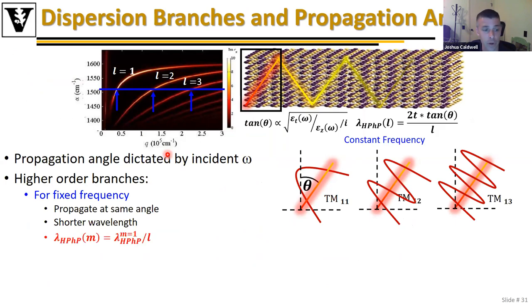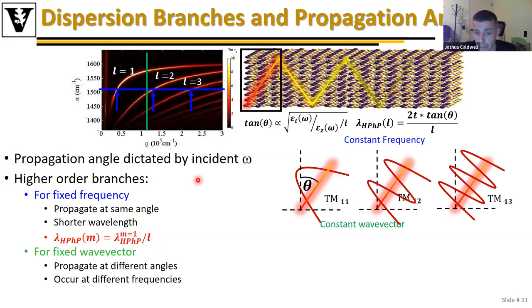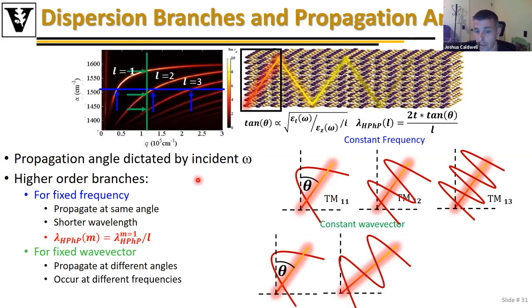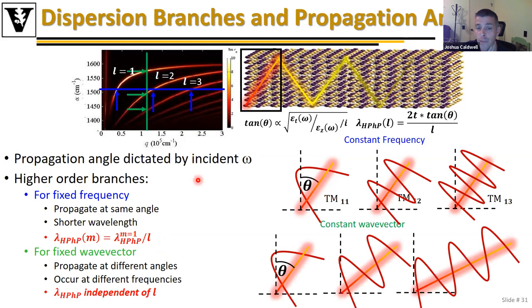And you can figure out the wavelength of that mode by looking at which mode you're talking about and the overall modal number that you're looking at. If I look at a constant wave vector, I now need to tilt that angle of propagation to support that same wavelength, but multiple orders of that mode, hence leading to this overall discrete structure as shown here. One of the interesting aspects of this is that your dispersion is therefore going to be dictated by the thickness of your slab.